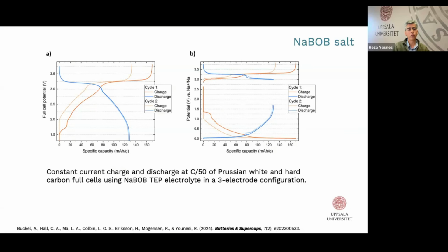The interesting part is if you look at the first cycle, somewhere around 1.5 to 1.7 there's a distinct feature on the first cycle when we charge the cell, when basically we form SEI. This is a very distinct feature for NaBOB decomposition.